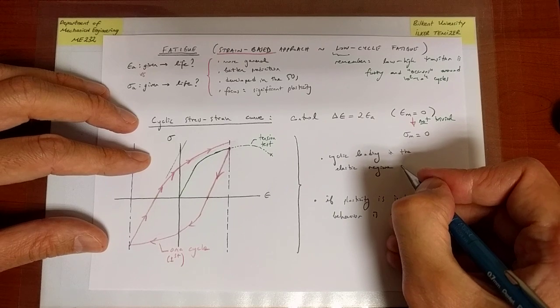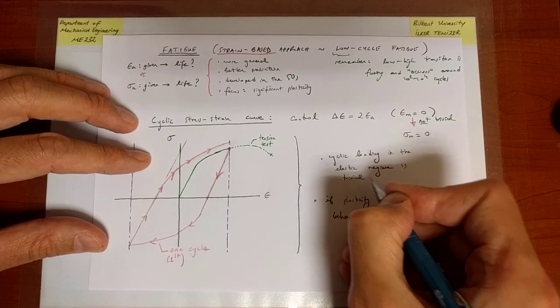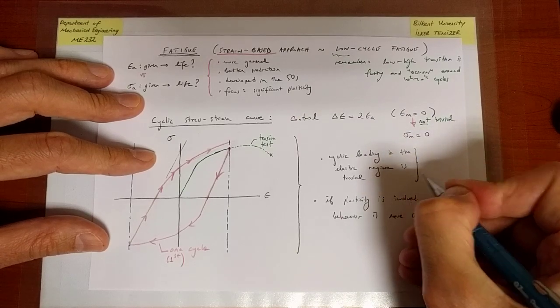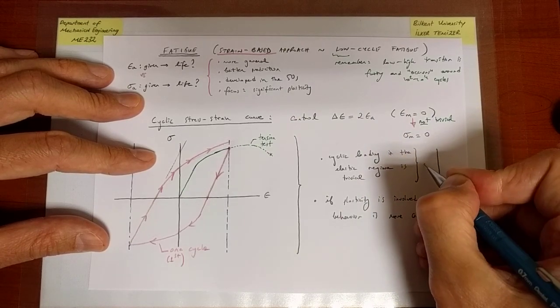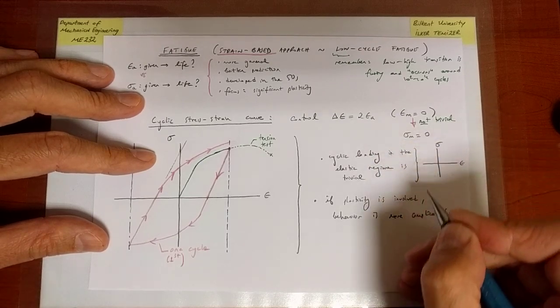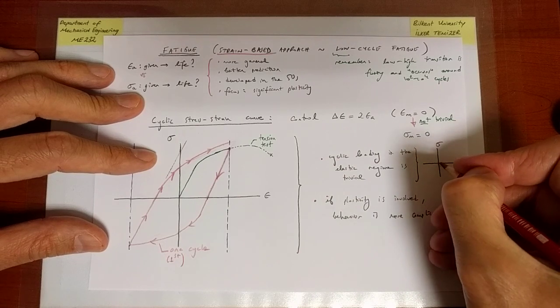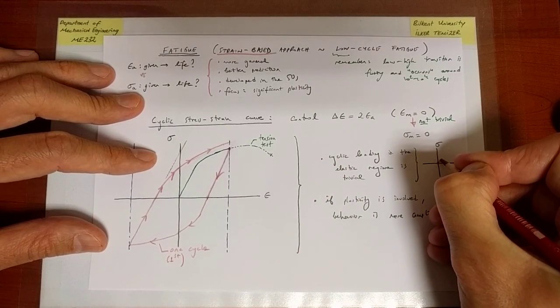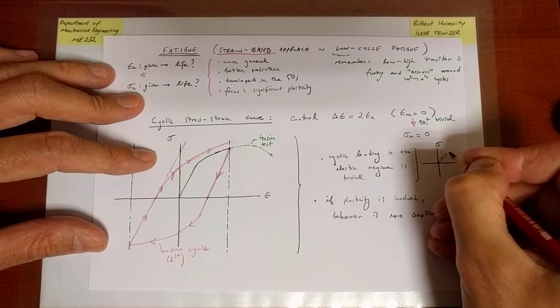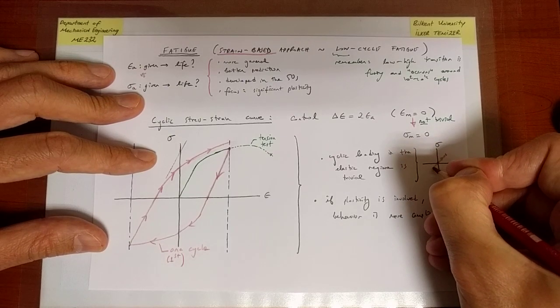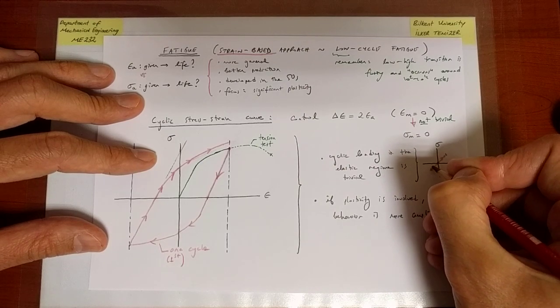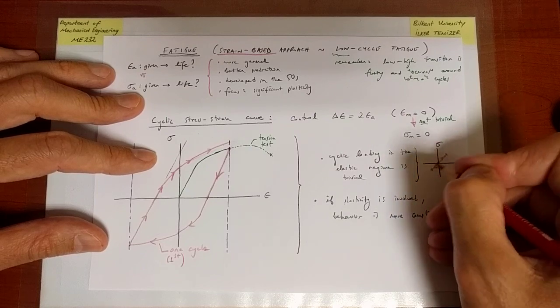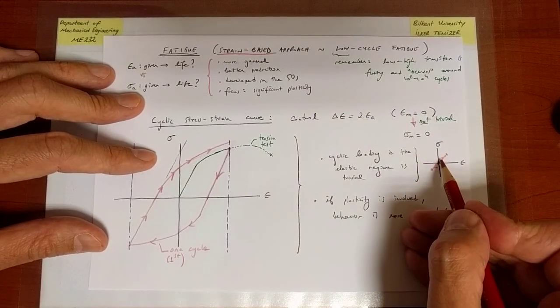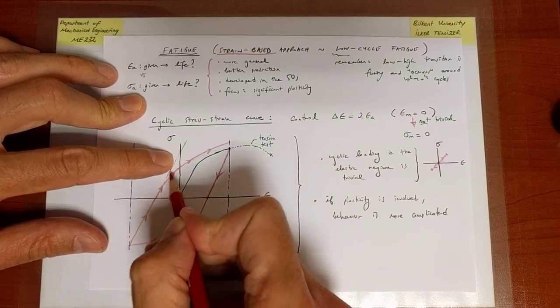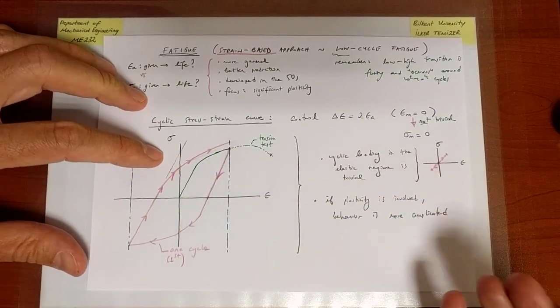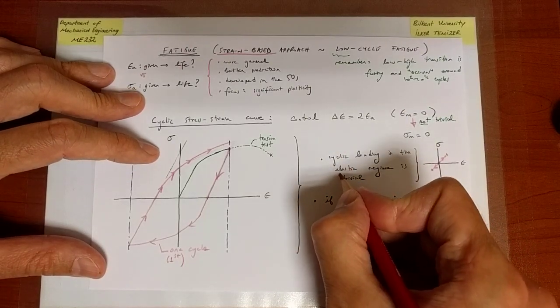then the behavior is really trivial, because what I would draw in that scenario is simply a stress versus strain curve where it doesn't matter how we start the cycle. We can start from zero stress-strain. I will increase up to a certain point. Let's say that point is well before yielding, and then I will unload, compress. It's well before reverse yielding under compression, and then unload back again and cycle back and forth, always on a line. I'm on a line. There is no gap forming between loading and unloading curves, let's say. And so it's just a line and sort of trivial, right? That's what I mean by trivial.